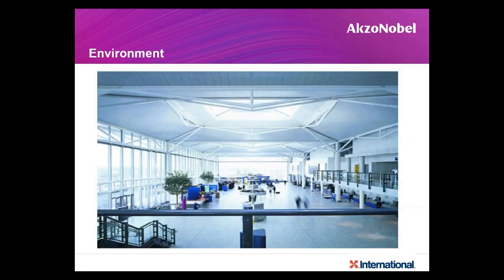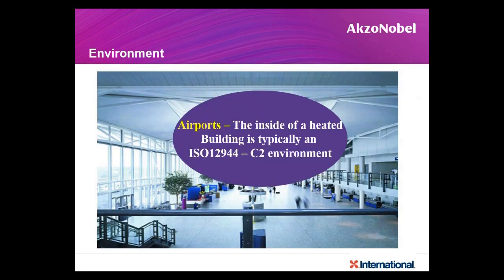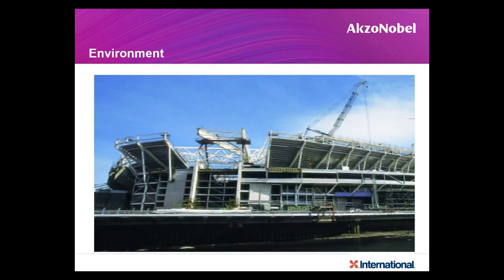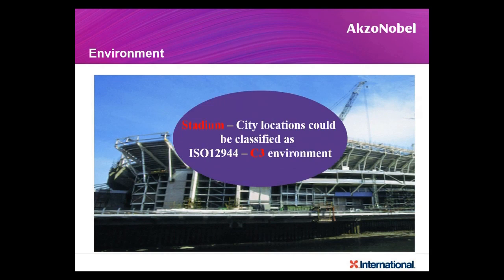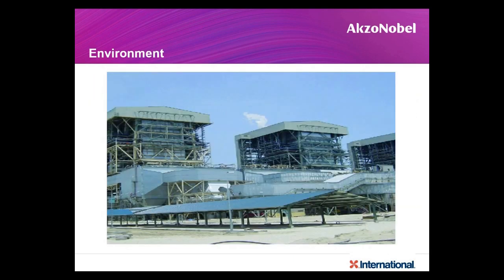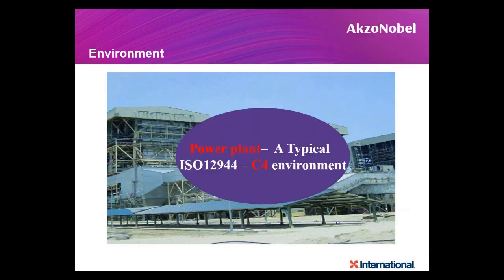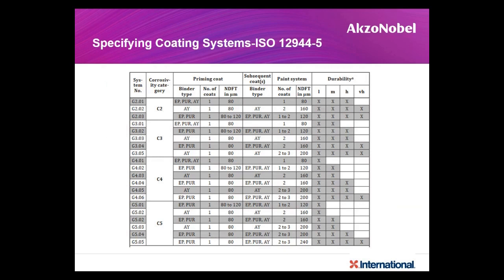For example, the environment for C1, C2 inside an airport, a stadium in the midst of a city, C3, a power plant, this is C4, offshore structure C5, CX. Now when you specify coating systems, when you look at this standard, it clearly gives you the binder type, what resin type you have to use, the number of coats, the nominal dry film thickness you have to apply, and what the durability is. Here you can see the durability.